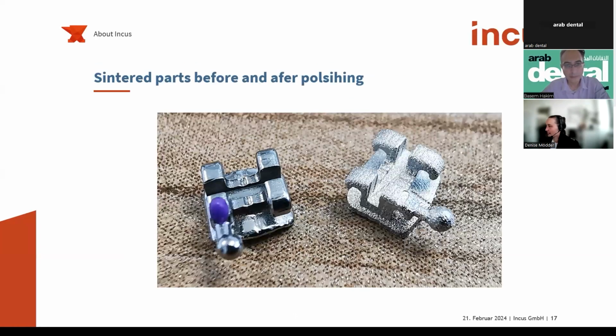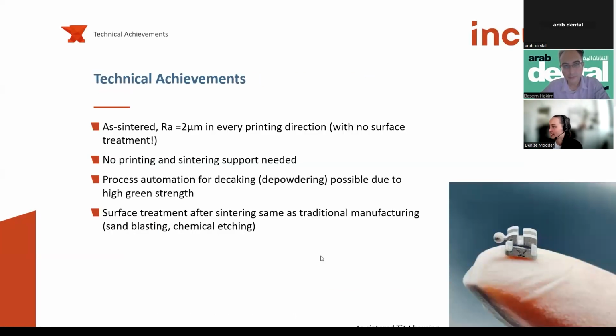I think this is one of the last slides, just showing polished brackets and as-sintered brackets. So this one will have a surface roughness of roughly 2 micron, while this one here is around 0.50 micron. So the achievement with our technology: no supports needed, surface roughness of 2 micron in every printing direction without any surface treatment. There's an automation process possible for the decaking, thanks to the high green strength, as well as for the cleaning of the parts. And the surface treatment after sintering is the same as any traditional manufacturing.